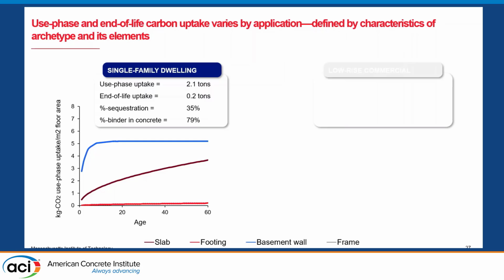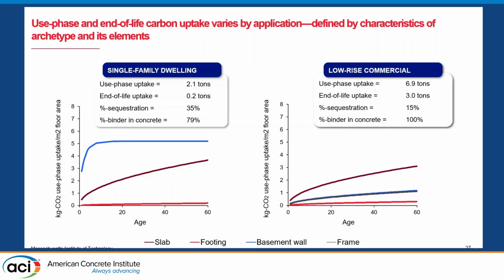Now, if we look at an example of a single-family dwelling, looking at the kilogram of CO2 use phase uptake per meter square of living area or floor area, a large portion of that comes from the basement walls, because the basement walls are CMU units and have this high potential for carbon uptake. And then compared to a commercial structure, basement walls are de-emphasized, and the CO2 uptake potential mostly comes from the foundation slab or the structural frame, where in the single-family dwelling, the structural frame was not assumed to be cast in situ concrete. And what we see is there's a differentiation between the archetypes in terms of carbon uptake potential per floor area.